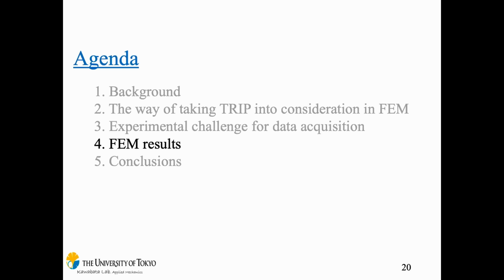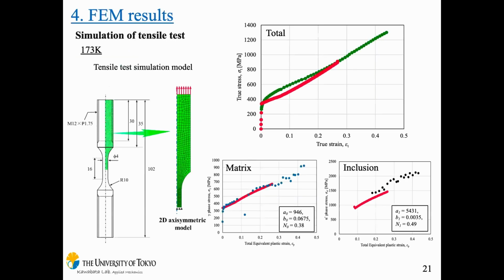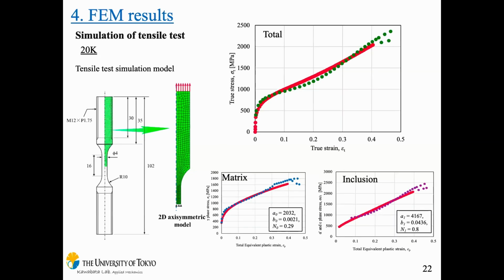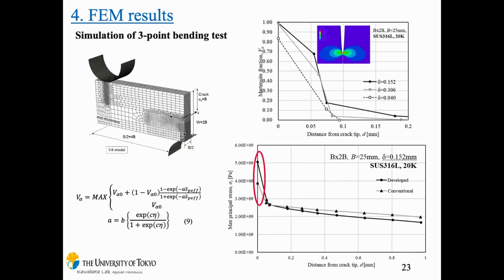Okay, so finally, I present some FEM results. Firstly, we conduct the simulation of the tensile test. After this FEM simulation, we get a result in good agreement between experiment and numerical analysis. When we use the 20K parameter, we also get a good result. Finally, I show the simulation of the 3-point bending test. The right graph shows the martensite volume fraction near the crack tip. So we can see that the TRIP occurs along with the deformation.